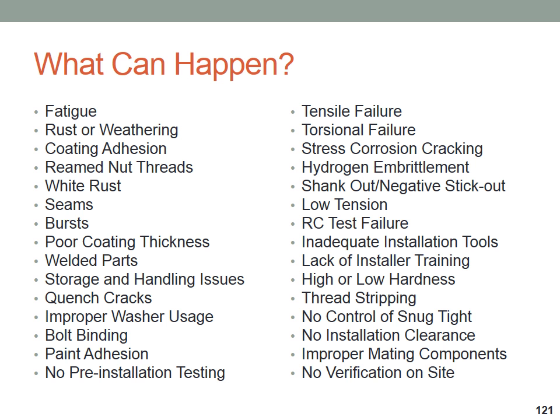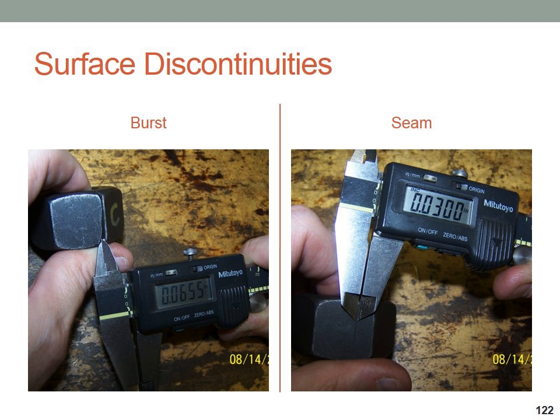And what we see quite often are surface discontinuities. There are relatively minor discontinuities that we would call a burst or a seam. Burst is sometimes a seam that opens up. A burst is sometimes just a result of the forming operation. Trying to move steel when it's cold occasionally causes the steel to sort of burst or split open on the periphery. Some people see that and sort of freak out, think it's an absolute big problem. In most cases that is not. It's sort of just a forging surface defect.